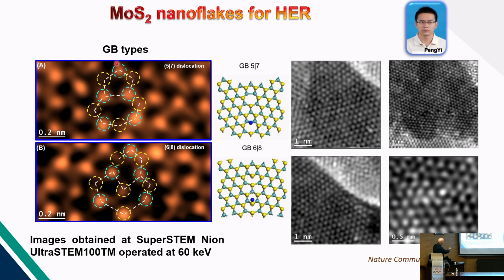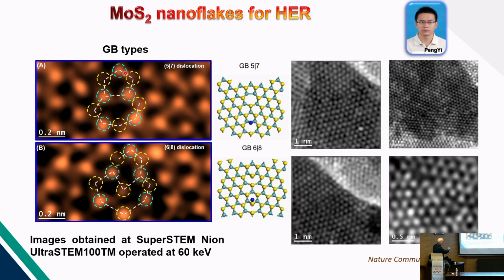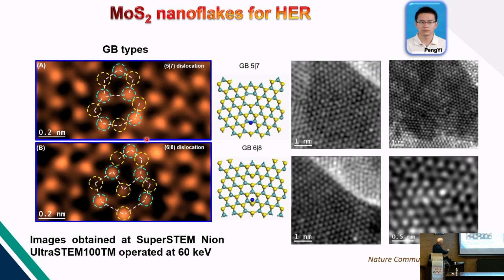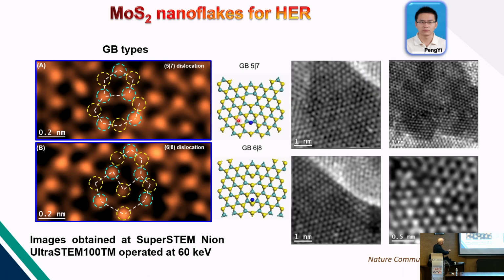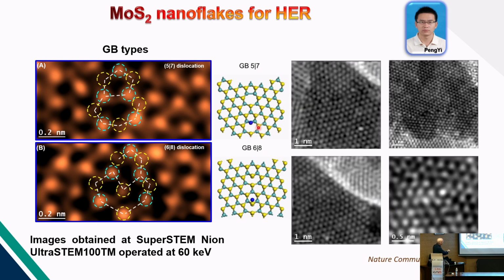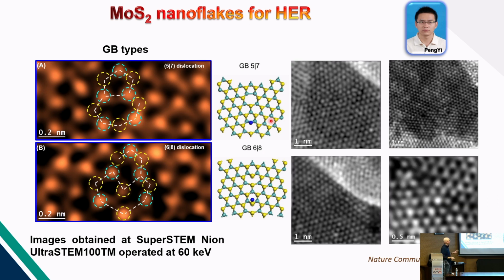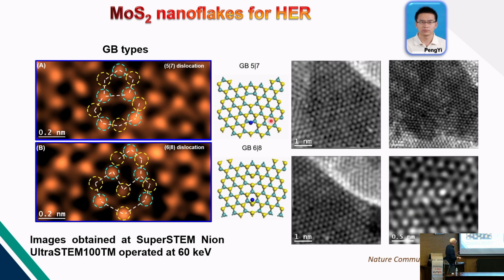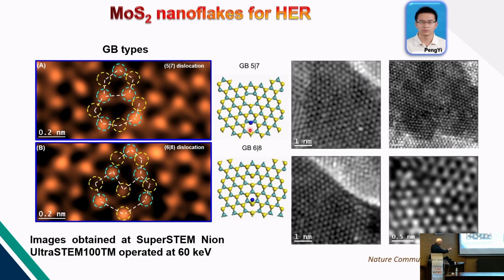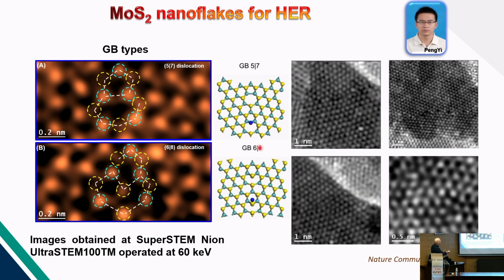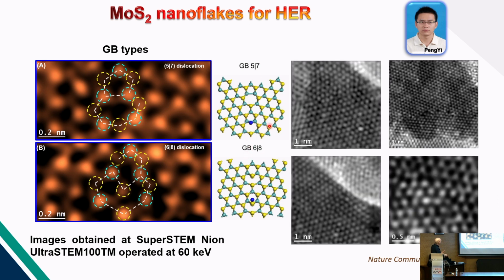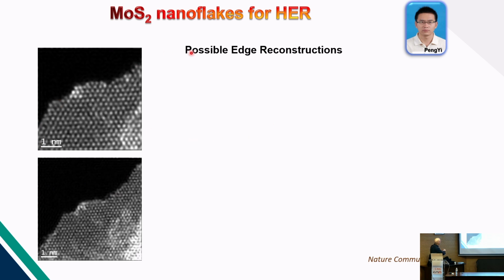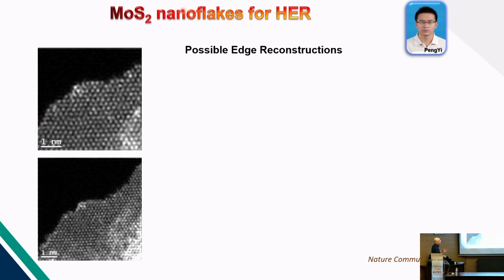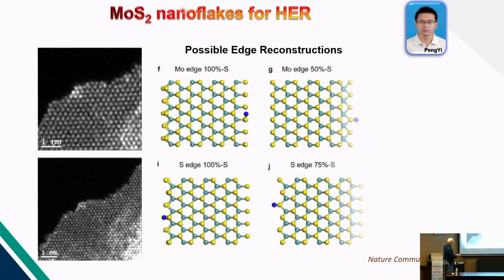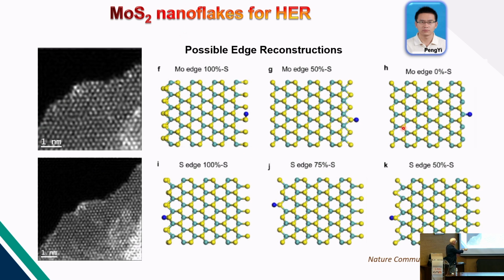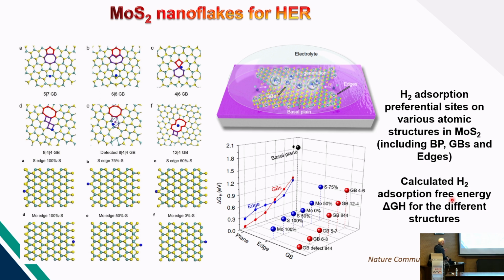With the TEM, what you can do is analyze that and see exactly which kind of defect you have, and by the simulation and the model, you can determine which would be the catalytic site that would be active in every one of the cases. So you just need to create the models of this, in this case for the grain boundaries, and also different models for the edges of the material, because the edges are really reactive as well. So you can get the different types of edges that you have in your material, and then you can get the simulations here.